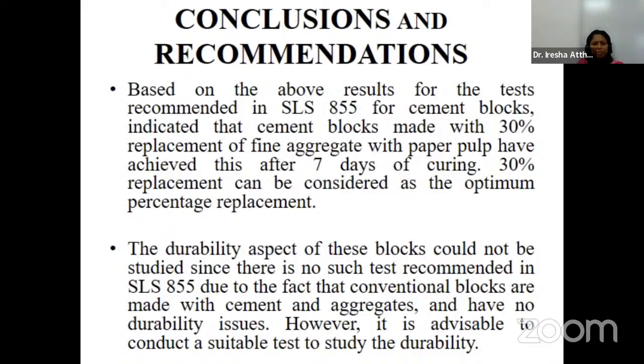SLS 855/1989 does not specify any curing period to achieve the specified compressive strength. It only says that this strength needs to be achieved the day blocks are taken out of the casting yard. Since the compressive strength results of cement blocks tested after 3 days of curing fail to achieve this, it is a requirement to cure cement blocks for 7 days in the casting yard. It also gives around a 14% reduction in dry density and a 10% reduction in wet density when compared to the control block. This reduction in self weight leads to substantial saving in the construction cost of structural elements. Further, even without any test results from this study, it can be concluded that savings are possible in energy cost due to the expected heat insulation property of added paper pulp.